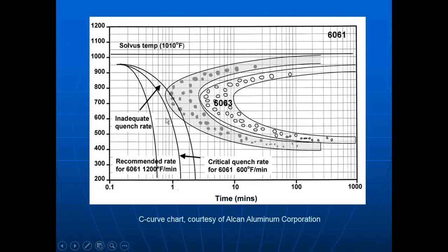This graph shows very well. I will go to the next slide for that. From here we see our three key characteristics. We need to enter the quench well before we reach the peak of the C-curve, the leftwardmost point. And that commonly for an alloy like 6061, we're looking to be above 900 Fahrenheit. Your customer might specify 920 or something similar, but we're looking for something in excess of 900.